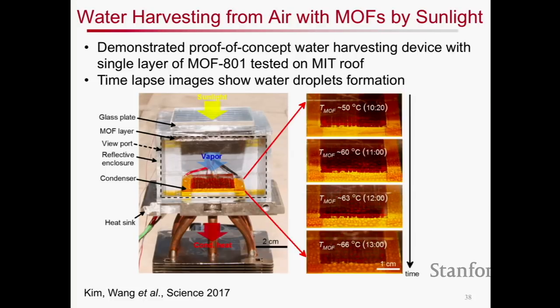What we show here is a prototype that we first tested, and this was done just on an MIT rooftop. What you see here is a single layer of this metal organic framework that's impregnated in a copper foam matrix. The reason for that is we needed something that has a relatively good thermal conductivity, but metal organic frameworks don't have intrinsically a good thermal conductivity. So that allows us to enhance the heat transport when we're facilitating the adsorption process, and the desorption process, I should say.